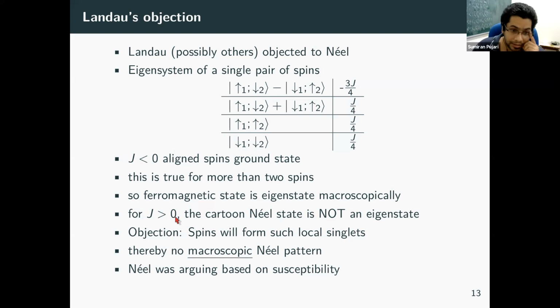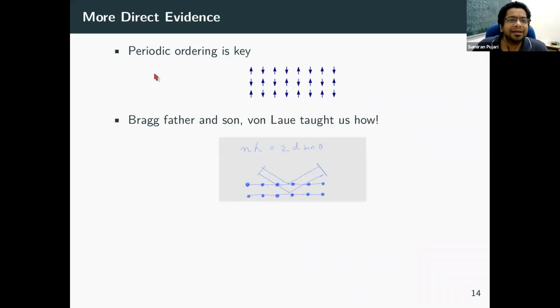And so that was the key objection that Landau made, that spins will tend to form such local singlets in presence of an antiferromagnetic Heisenberg interaction. Therefore he objected that there should not be any macroscopic up-down, or Néel, pattern. Whereas Néel was arguing, I suppose based on susceptibility measurements, that something special is happening on the low temperature side in some materials. So the real direct evidence of whether we have this up-down Néel state or not, the key point is whether there is periodic ordering in the sample. Is this up-down pattern really present or not?